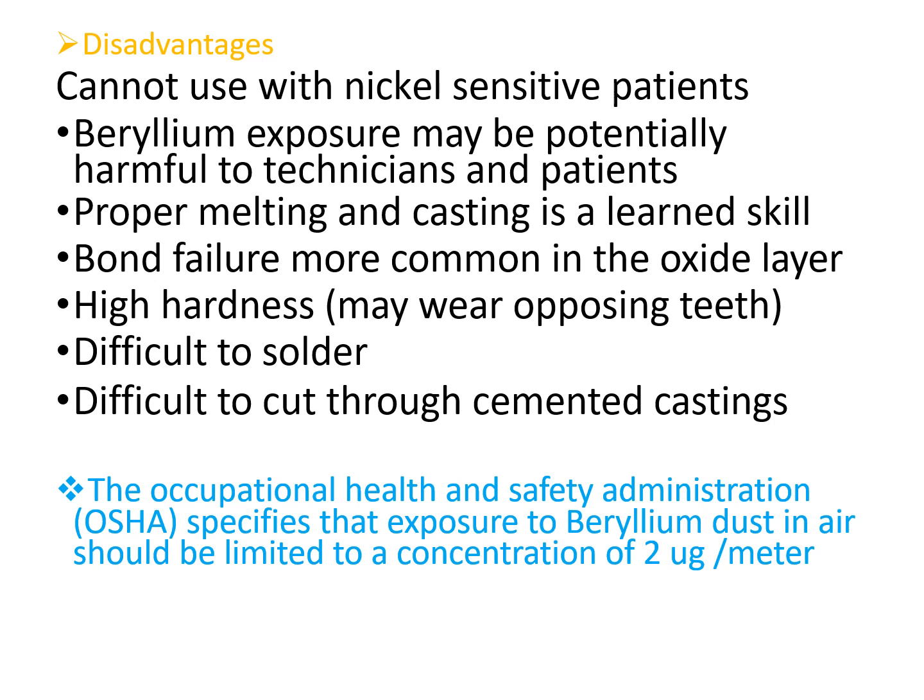The disadvantages are that it cannot be used in patients with nickel sensitivity. The beryllium exposure may be harmful to technicians and patients. The proper melting and casting is a learned skill. Then the bond failure, which is very common in the oxide layer. And high hardness, it may wear the opposing teeth. It is very difficult to solder and difficult to cut through cemented castings.